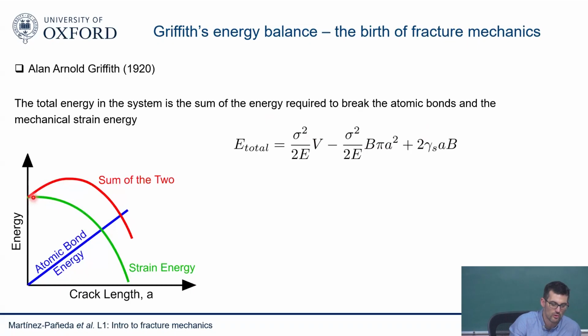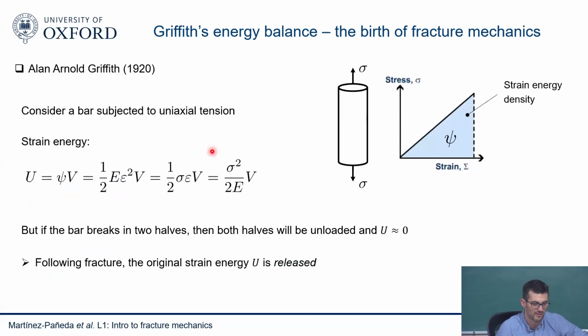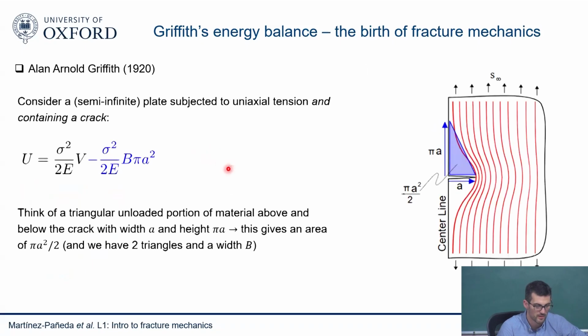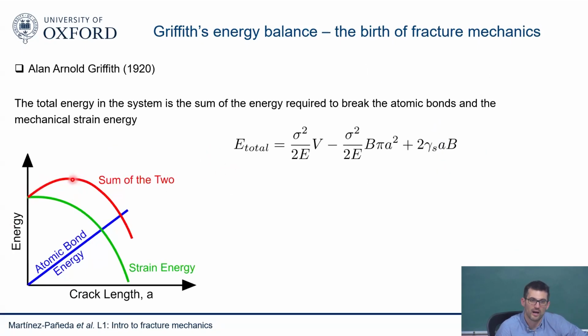And you can see that we're growing, growing, but eventually we reach a point. When my crack is very small, I need to keep putting energy in. I need to keep increasing the load in my sample in order for my crack to grow. This curve is going up. I can only grow my crack if I keep putting energy into it. So I need to keep increasing my applied load. Remember, the mechanical strain energy increases with my applied load. But then eventually I get a point where I don't need to apply any more load.